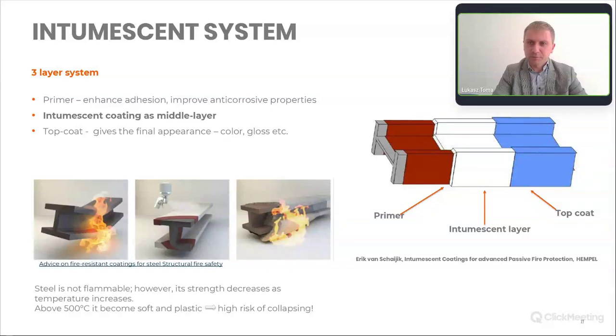And intumescent system. So it's one of the very specific applications of such coatings for the protection of steel. They can be used for the production of hydrocarbon intumescent coatings. And for maximum protection, usually we apply a 3-layer system. So we have a primer, which improves the adhesion to the steel and also provides some anti-corrosive properties, our intumescent layer, and the top coat just to give good finishing, good appearance of the coat, and hence the gloss color, and also, to some extent, improve the barrier properties.